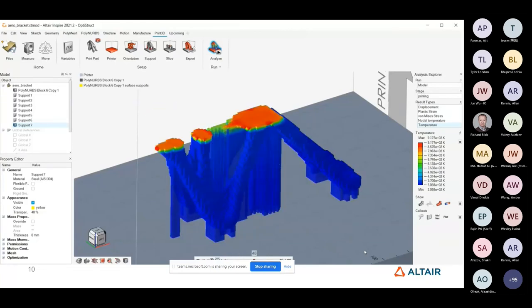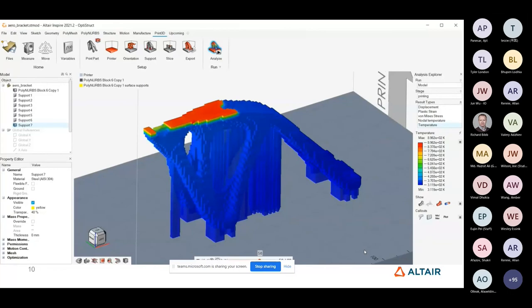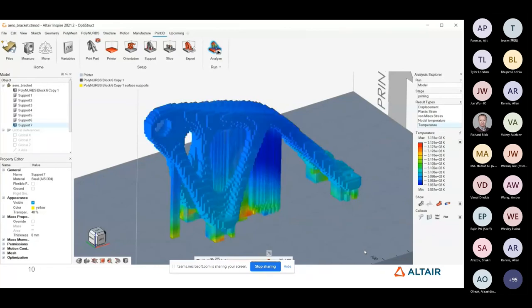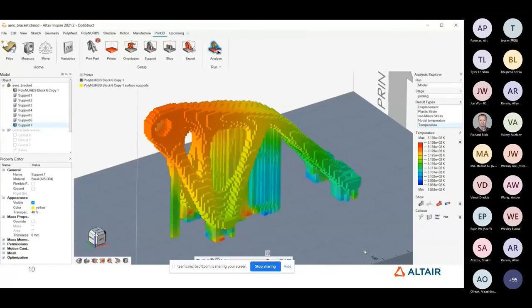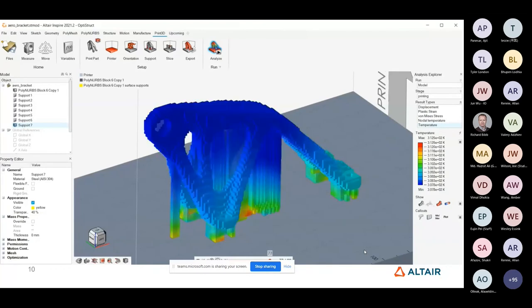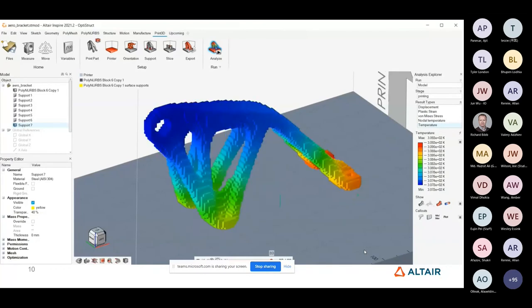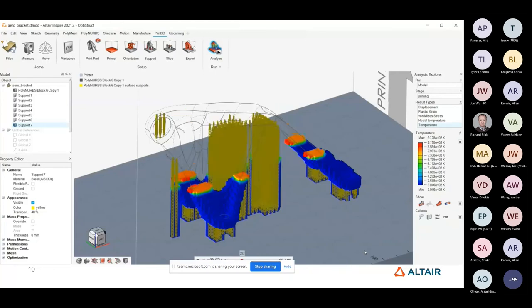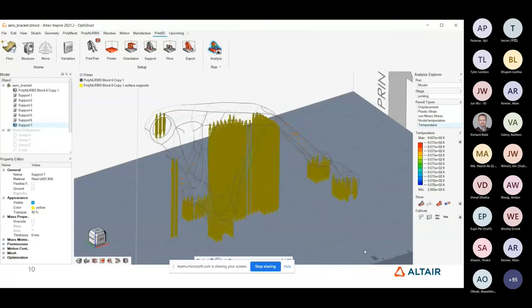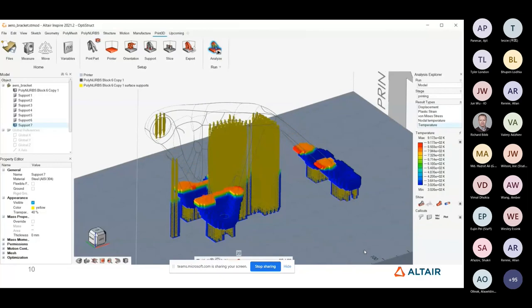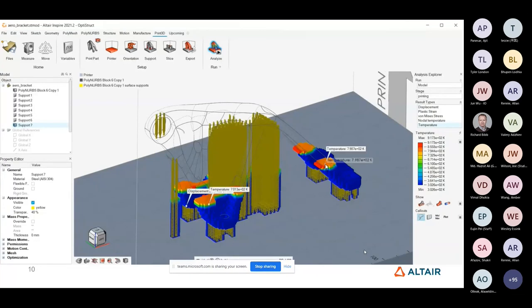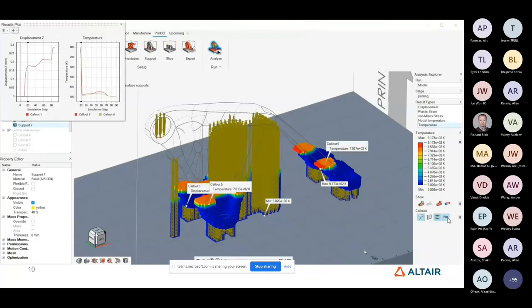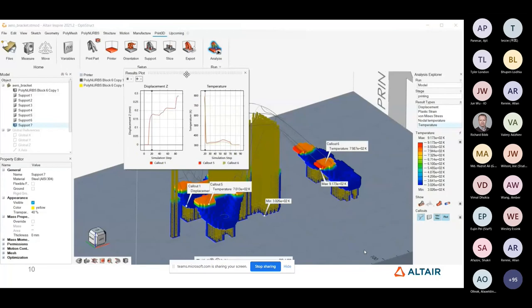So they can get a feel for whether there's likely to be any failures during build. And we can see how the temperature is changing in the part as well, to see how effective those support structures are as acting as heat sinks to try and take some of the heating away. So we provide this ability to view these results to try and inform the designer as to the viability of their design. We can turn on the undeformed parts here so we can see how that compares. We can obviously take individual measurements, individual layers, identify minimums and maximums, and we can generate as well graphical plots as well of all these results so we can see how they vary over the simulation step also.